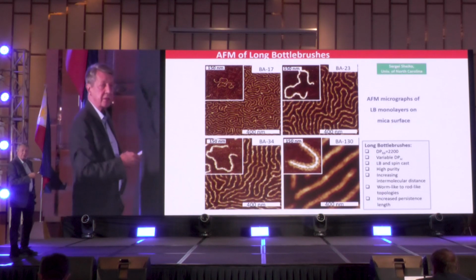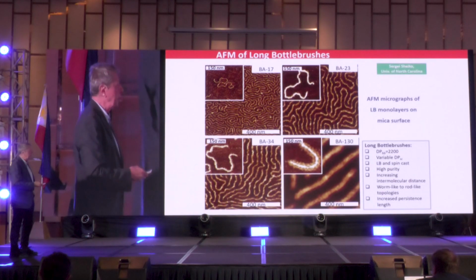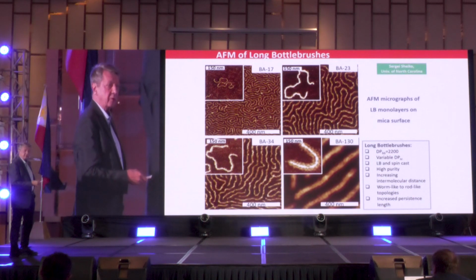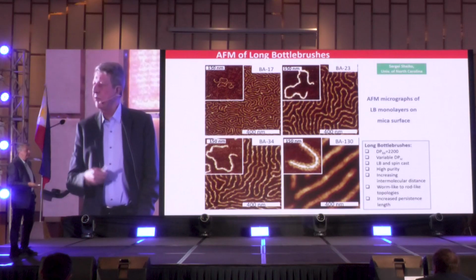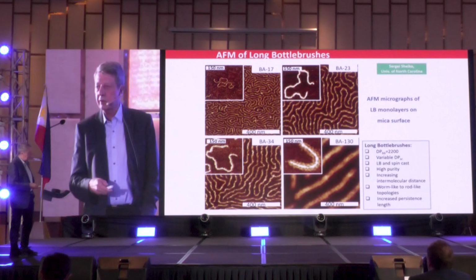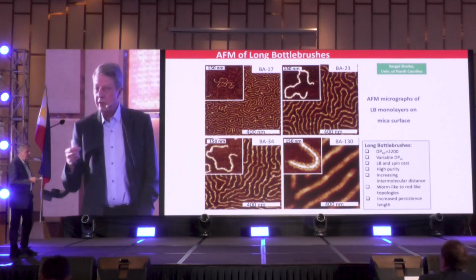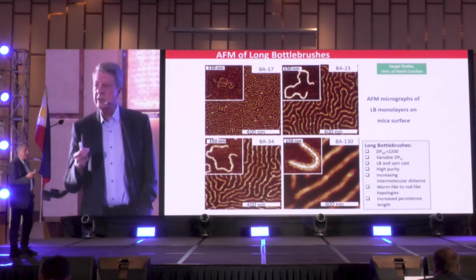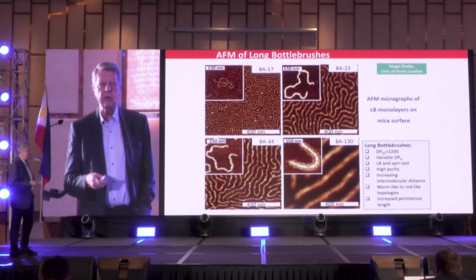And you could see these images of the polybutyl acrylate side chains with a backbone around 2000. So they are, roughly speaking, half a micron long. And you could see what happens if I grow a longer side chain: 17, 23, 34, 130. They are becoming more stretched. And also, if you go to the next slide, you could see how it affects mechanical properties. Next slide.